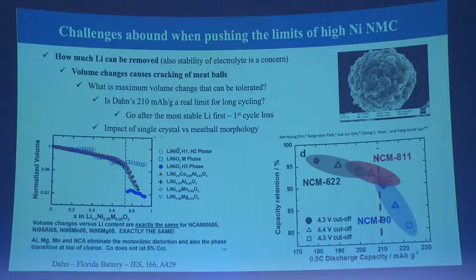And what I didn't mention, all lithium-ion batteries, when they're manufactured, are cycled between 3 and 5 times at the manufacturing plant to form a protective, what we call SEI layer on the surface. Once that's done, the gas is let out, fresh electrolyte is put in. But if these things crack in use, then you're making fresh surface, reacts with the electrolyte, and that raises the resistance, but more importantly, it uses the electrolyte up. Lithium-ion batteries, for the most part, are like your alkaline cells. If you open them up, nothing should drip out. It's a minimum amount of electrolyte in there to give you the highest energy density.